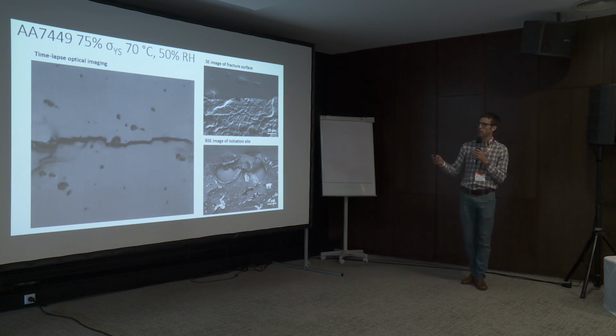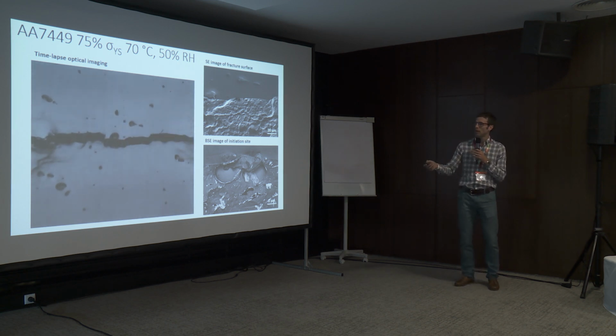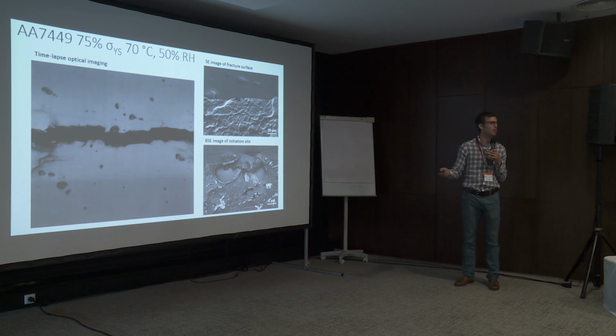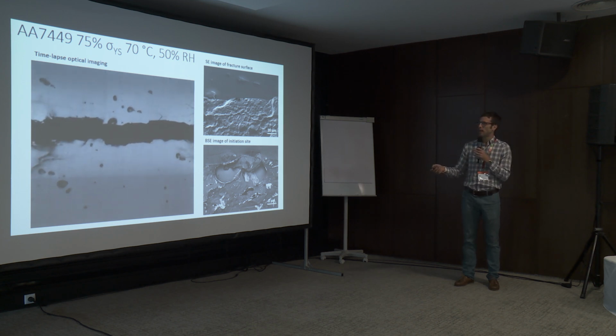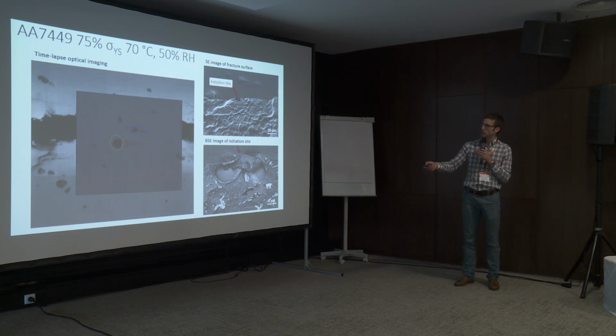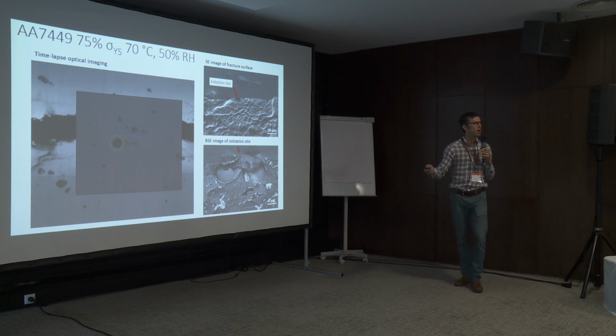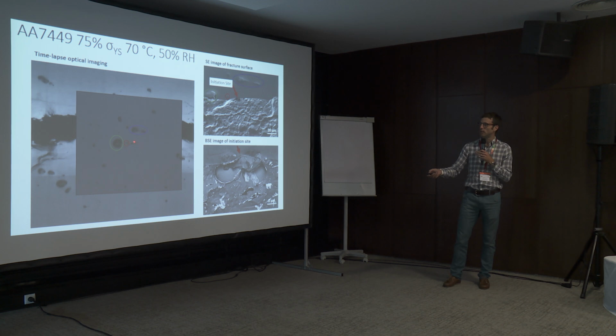So watch these 3 sites, because this is when we zoom right into the image. It's a very high resolution image made out of all of these tiles, and we can see that exact point of initiation of these cracks. And it's interesting that that point of initiation is actually this feature here, which is right next to some very large features, and it's really not where you might have guessed the crack would have started.